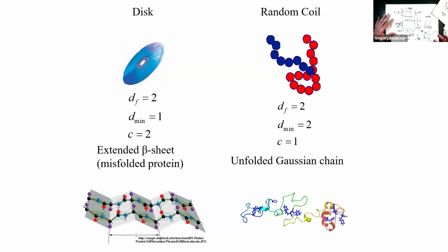So it's denser when you bind it. And the density that it reaches is the Gaussian density. Kind of odd, this kind of material is exactly like polymer coils. Things behave in the same way. And when it's avoiding itself, you get this 5/3 dimension, which is called the self-avoiding walk in polymers. You have a Gaussian walk and a self-avoiding walk, like two limiting cases.